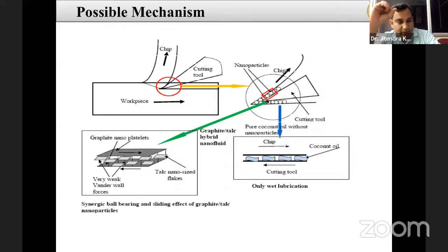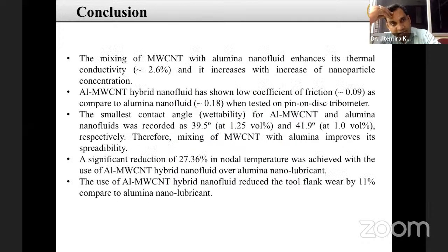And this possible mechanism, I already told you: when hybrid cutting fluids come into the contact, then tribofilm formation happens. So the conclusion from this is, we also tested the contact angle, and there was a significant reduction of 27.36% in nodal temperature, and flank wear is reduced by 11% in case of the hybrid nano cutting fluid. Mixing of MWCNT with alumina nano cutting fluid also enhances the thermal conductivity, which we tested with the portable thermal conductivity meter, and it increases with increase of nanoparticle. So thermal conductivity of the fluid is also a very important parameter in case of the cutting fluid.